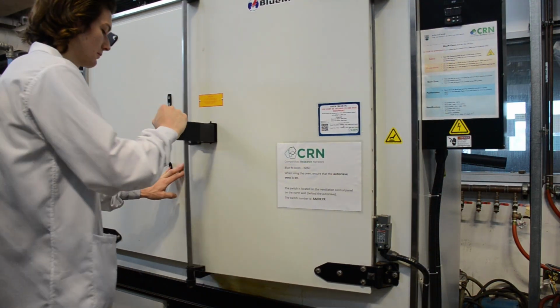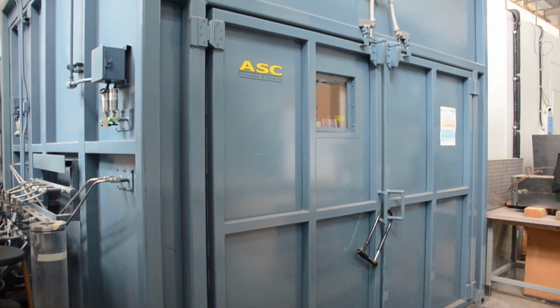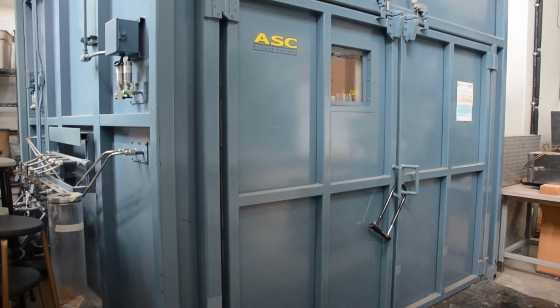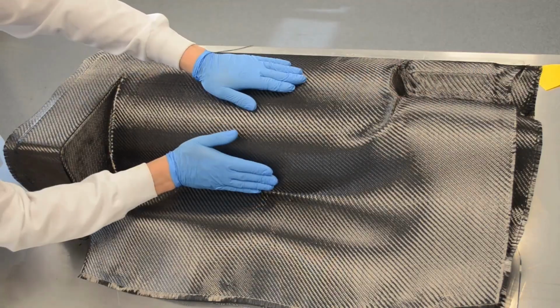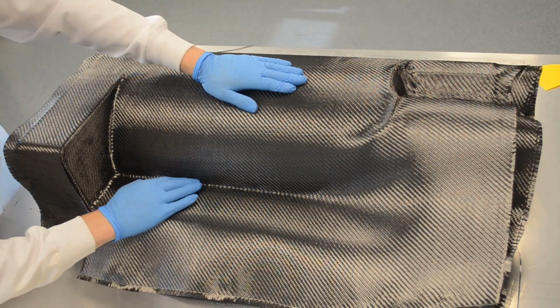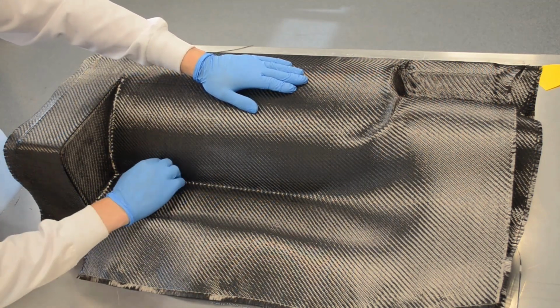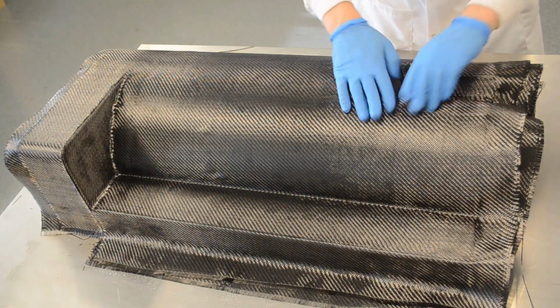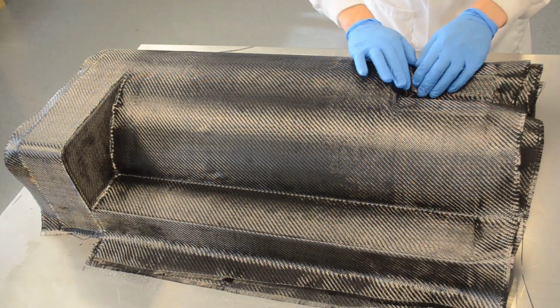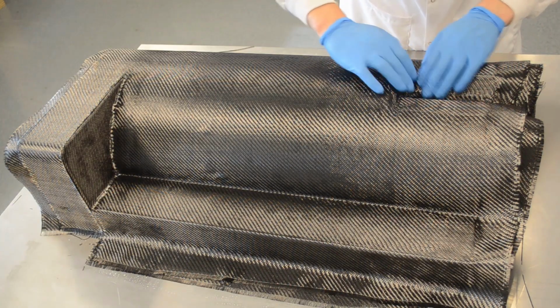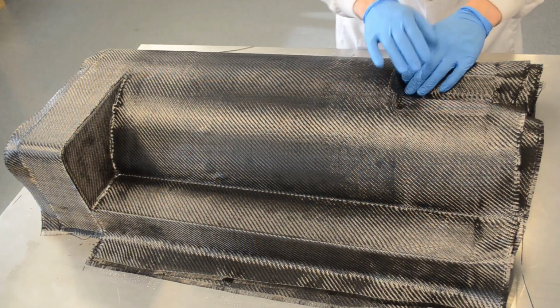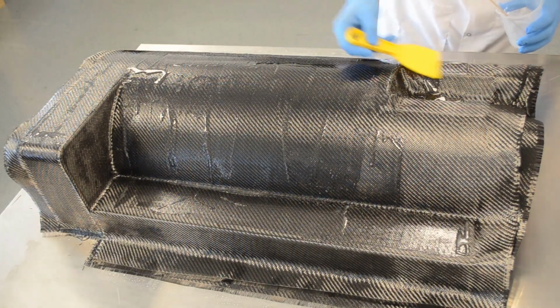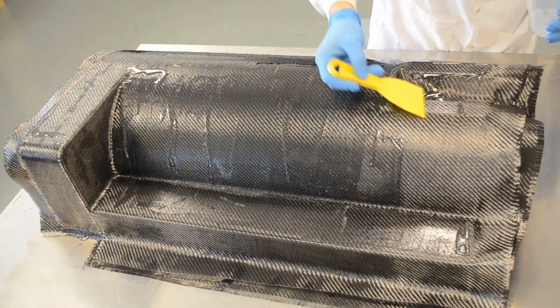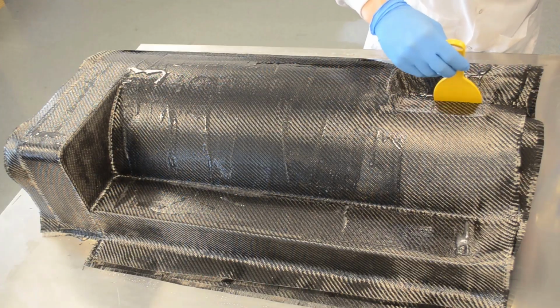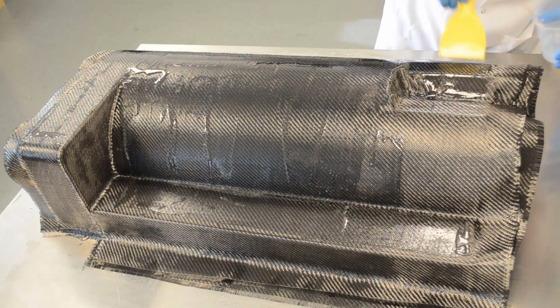In a production environment, either of these requirements could increase the cost of the part, as more storage space or equipment would likely be required to produce parts at a fixed rate. A factor that has a significant effect on part outcomes is laminator skill. These parts were fabricated by a laminator with some previous wet layup experience, but part quality can be improved by employing professional staff and producing a number of practice parts. Fiber alignment, bridging, wrinkling, and uneven resin content, as well as fabric placement and uniformity of appearance, are all improved with laminator skill. After performing a handful of wet layups and observing their outcomes, a few conclusions can be drawn.